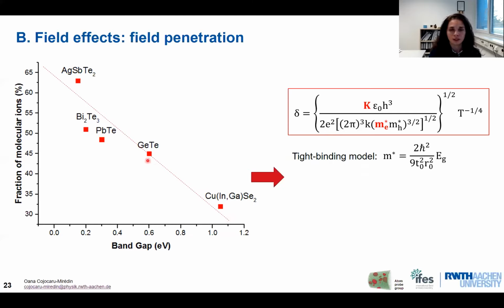And then we have other materials, typically phase change materials like GeTe. The thermoelectric community also started to use this compound for their applications. And we have here basic thermoelectric materials like lead telluride, bismuth telluride, and silver antimony telluride. And we see nicely that there is a certain trend between the fraction of molecular ions and the band gap. Again, this is simply because having a lower band gap, we have a lower effective mass of the electrons, and we have a higher field penetration depth. A higher field penetration depth might be a reasonable explanation why we end up with a higher fraction of molecular ions in the mass spectra.